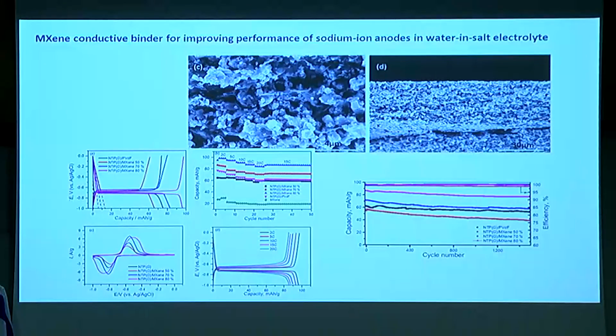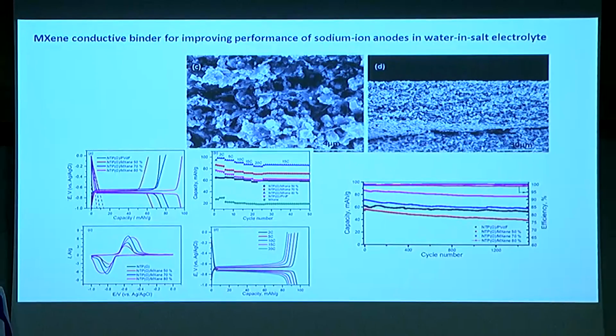The last system, I will just describe shortly. It's about a sodium-ion battery. Here we work with NTP, sodium titanium phosphate. It has a very nice plateau in a concentrated 10 molar sodium perchlorate electrolyte, at about minus 0.7 versus Ag/AgCl. And here the idea is that we have the PVDF binder, which is inactive mass. So why not try to change the binder to some active binder? So here we use, again, MXene. MXene has good binding capability, it has electrostatic interaction, and we were able to increase the mass loading of the active particles up to 80% of the electrode.